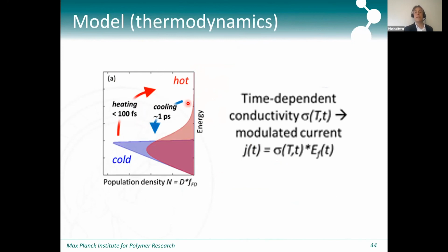where we have this cycle of heating and cooling, and especially this cooling step, the rate of that is determined by the electron phonon interaction. And indeed, you can manipulate that to some extent. We've actually spent a lot of time trying to do that, and we only gain a factor of 2. It's not the order of magnitude effect that one might have hoped for. So you can indeed manipulate the electron phonon coupling, also through the phonon density of states, and enhance the effect, but it's very limited. And the size of the substrate doesn't matter, because it's really the electron phonon coupling within the graphene layer. So the transfer of heat from graphene to the substrate is even slower.